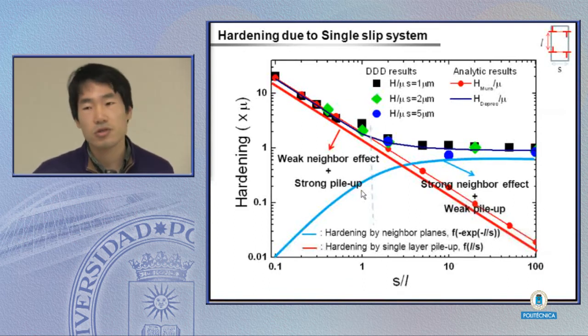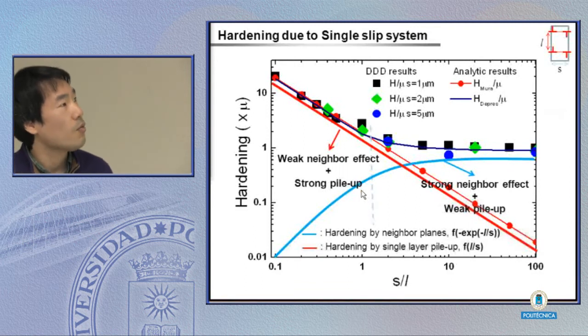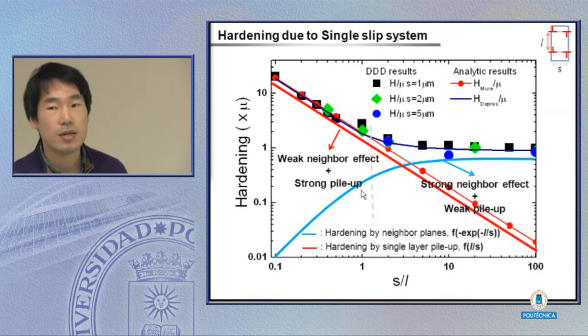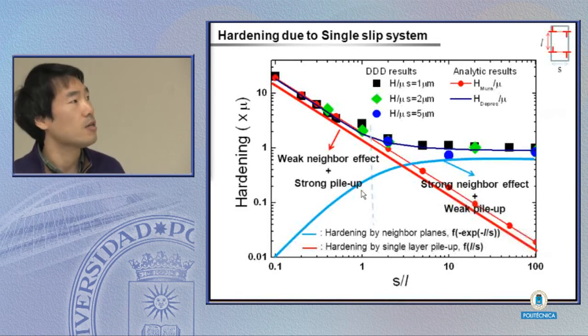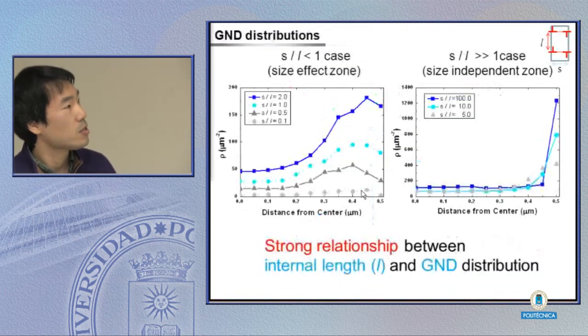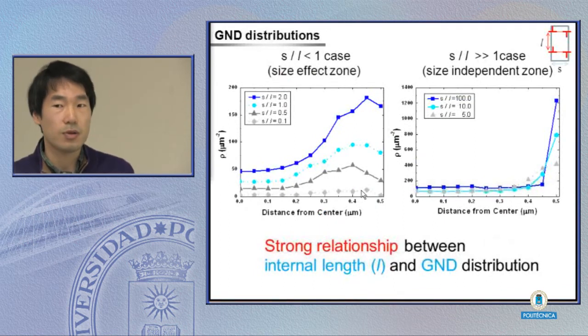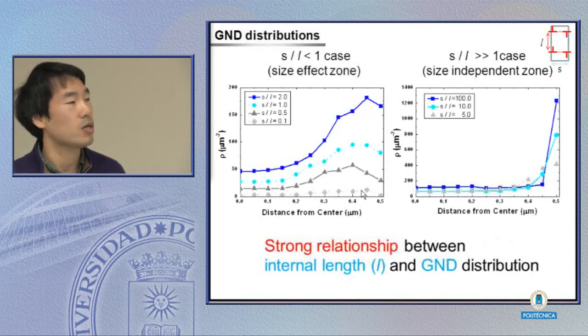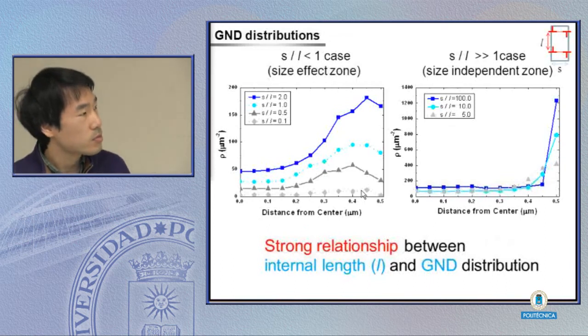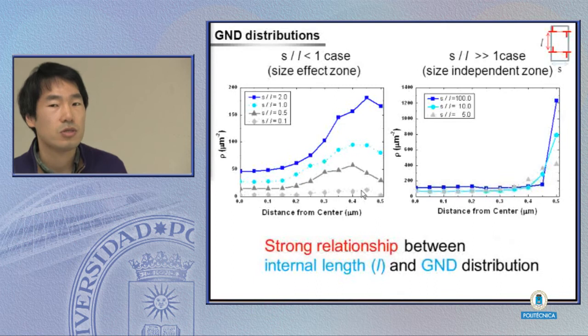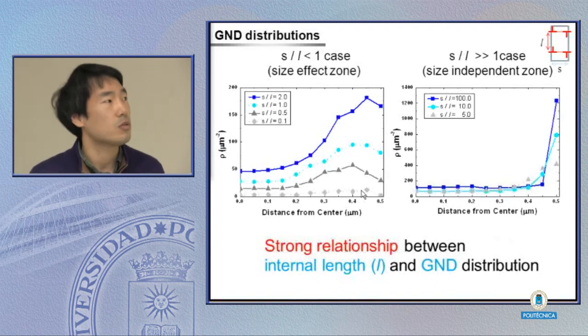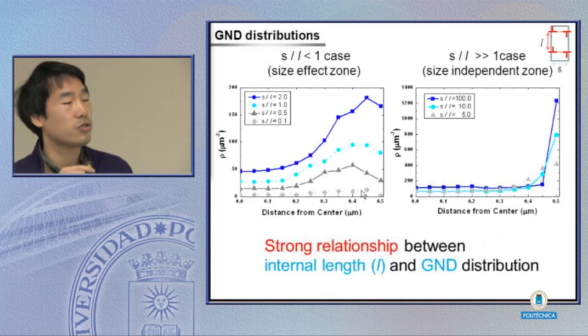The reason is there are two kinds of hardening mechanisms. When the distance between two slip planes is large enough not to feel each other, the hardening is only due to the pile-up in one slip plane. On the other hand, when decreasing the length between two slip planes, the interaction between the slip planes also gives the work hardening. So this is the reason why the Mura solution doesn't match the discrete dislocation dynamics result. The Mura one doesn't consider the interaction between two layers.